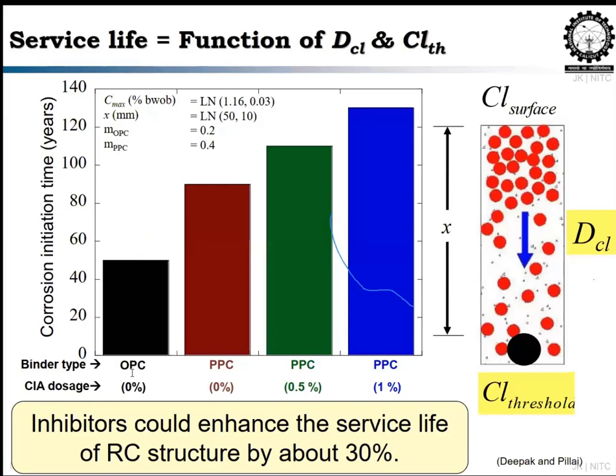For example, if you don't have any inhibitor in the case of OPC, corrosion initiation is expected at 50 years. But if you are using PPC, this is very, very important. You don't need any inhibitors or anything. Just using PPC of 0%, you can see the service life increase to almost 90 years. That is the major takeaway. Here the water cement ratio is 0.4.